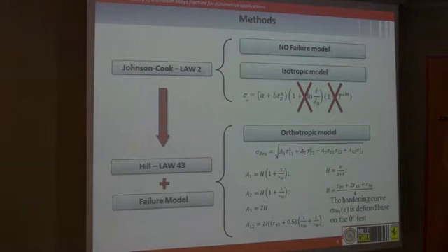By tuning the Lankford parameters R00, R45, R90, it is possible to derive a set of feasible A constants which suitably predict the 0, 45, and 90 tensile tests. These constants affect the equivalent stress value for 3 uniaxial numerical test cases, whose results have to be concurrently correlated.